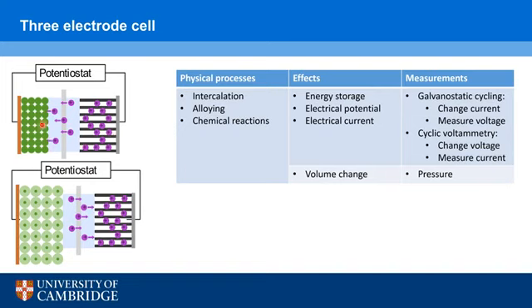We then have an anode and a cathode, and we use a potentiostat to measure the potential difference between the anode and cathode. But the problem there is that in a full cell, because the potential of the two materials are simultaneously changing, the potential difference gives us a measure of the voltage between the two materials. But because both materials are changing, we can't track the chemical changes at each electrode separately.